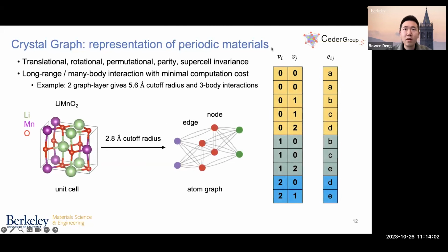To answer this question, let's take a look at how atoms are actually represented in machine learning interatomic potentials. In our work, we use a crystal graph as a representation for periodic materials, and these crystal graphs are constructed by searching for the neighboring atoms for each atom within a cutoff radius. For example, if you look at the lithium manganese oxide unit cell on the left here, using a 2.8 angstrom cutoff radius, you get this atom graph on the right. The color corresponds to each type of atom. You can see, for example, the manganese has 6 neighbors here, so it has 6 bonds connecting to different nodes.